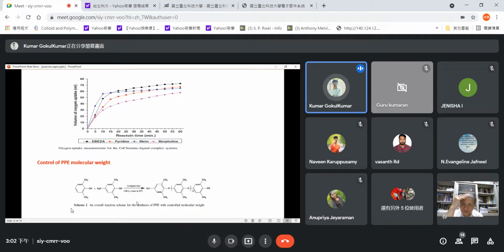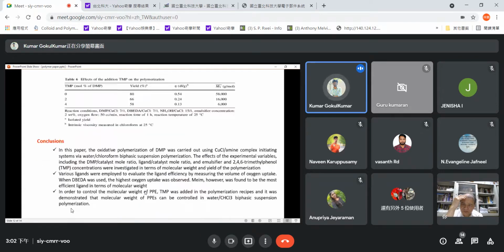The reaction was performed without addition of TMP, and with addition of TMP. Without TMP is 0, and with TMP it is 2 weight percent and 4 weight percent. The table clearly shows that the molecular weight depends strongly on the amount of TMP added, making it possible to control the molecular weight of PPE.